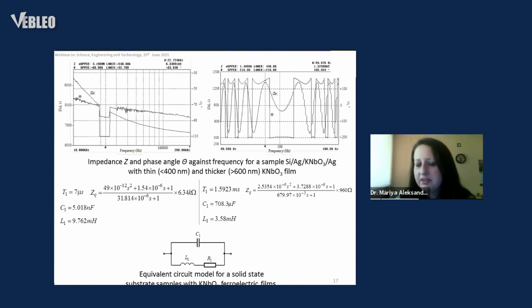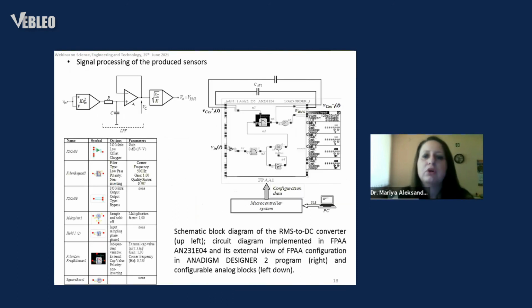We found that the potassium niobate is strongly sensitive to the thickness, and if the thickness is greater than 600 nanometers, some overtones could appear in the characteristics, so they can introduce noise in the sensing channel, so such thicknesses should be avoided. This is from the design point of view.